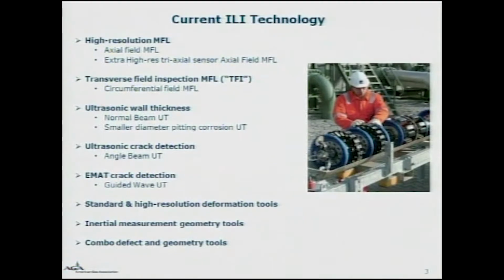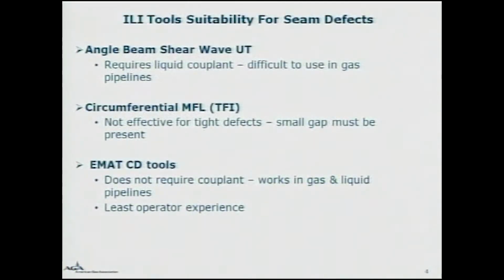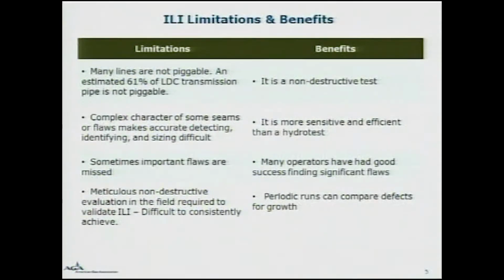As described in detail by Mr. Foreman and others, there are numerous different ILI technologies. Again, the tools are selective, and operators must know the defect they are searching for and use the specific tool. As stated, certain tools have better abilities for seams and cracks, but no tool is 100% foolproof, and there are limitations. In order to run inline inspection tools, the pipeline must be piggable both physically and operationally. And what I mean operationally is that pipeline flow rates and operating pressures must match the tool speed requirements. Inline inspection can detect corrosion, mechanical damage, material defects, and cracks. Operators support the technology, but acknowledge the limitation that it is never 100%.